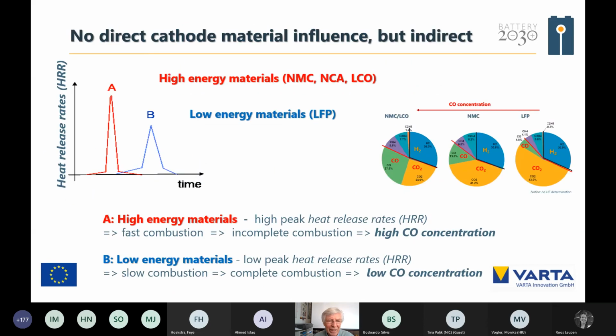If you are looking at the heat release rate over time, we have two groups. You have the high energy materials, the NMC and the LCO. You have an early start of the heat release and with a very high maximum. And then you have the low energy materials like LFP coming later, and the heat release rate is not too high. So in case of the high energy materials like NMC and so on, you have a fast combustion. And fast combustion means incomplete combustion. And incomplete combustion means you have a high carbon monoxide concentration. And in the low energy materials, you have a slow combustion, complete combustion, and a low CO concentration, which you could see in that case.